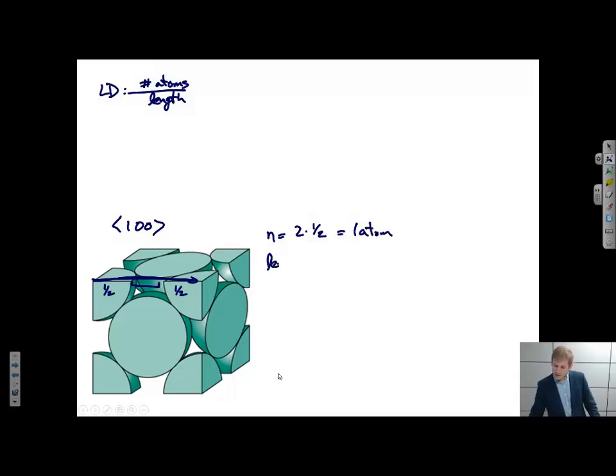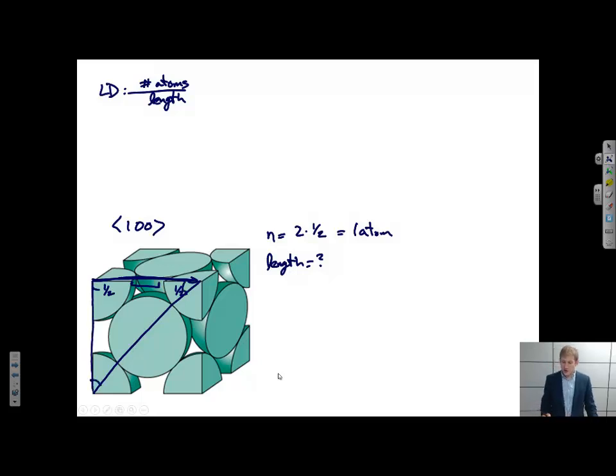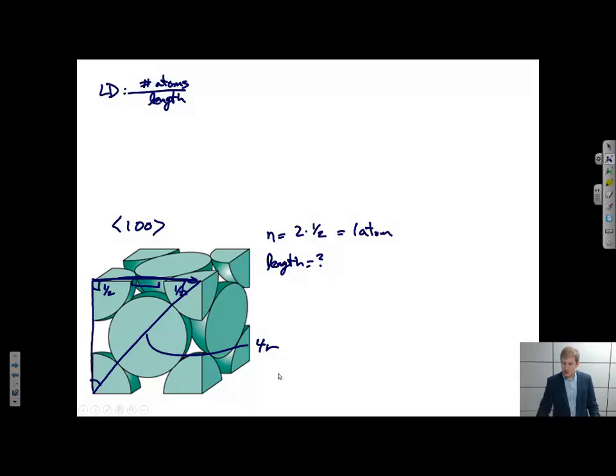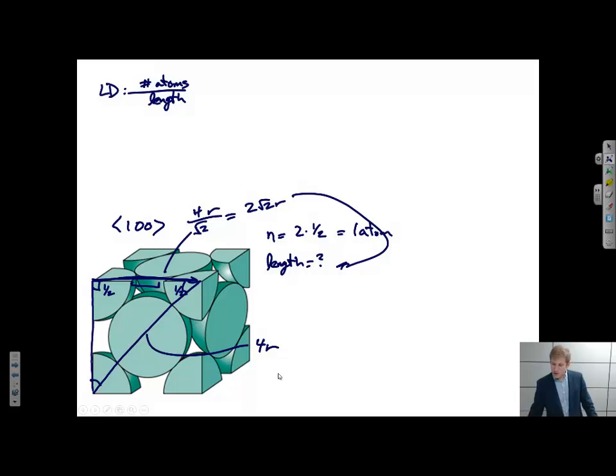The length is not clear at first. You'll find that oftentimes when dealing with linear densities, planar densities, and atomic packing factors, it all comes down to drawing the right kind of triangle to get the length you want based on things you know already. If I draw a triangle like this, it's going to be a 45-45-90 triangle — I'm just bisecting the front surface, which is a square. I know this hypotenuse is 4r. So each of those legs is going to be 4r divided by the square root of 2, or 2√2r. That is the length of the line in question, so the linear density in this case is 1 over 2√2r.